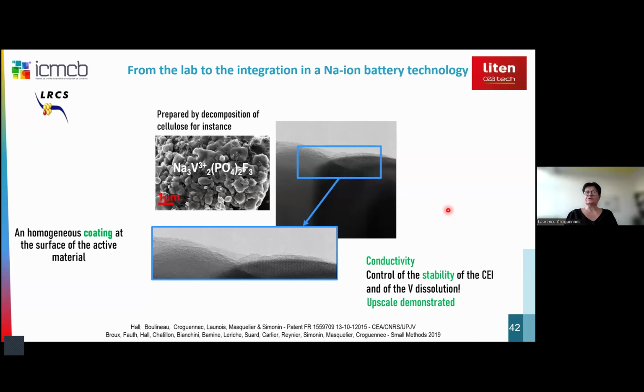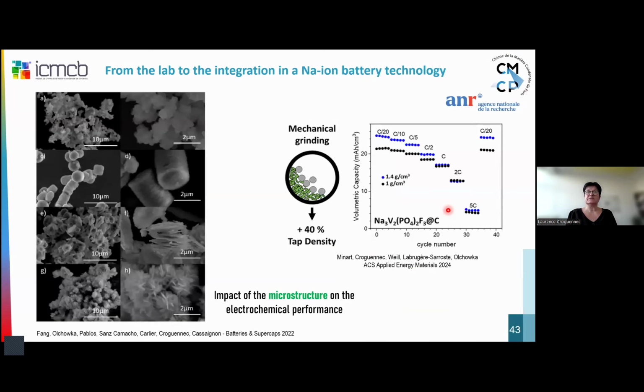The homogeneous coating is the key to the performance of these materials. Of course, it brings conductivity within the electrode, but it also brings stability of the CEI, and especially stability versus vanadium dissolution. And we were able to upscale these materials.